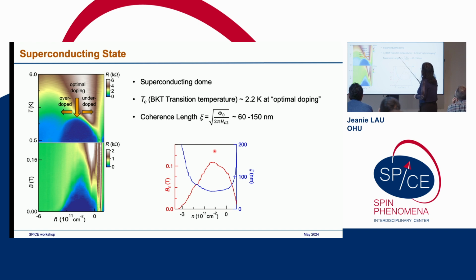The TC we define as 20% of the normal state resistance, and that's 2.2 Kelvin at the highest doping. But the practice these days is to take 50% of normal state resistance, and in that case it will be about 3.1 Kelvin. And that will be the highest superconductivity in twisted bilayer graphene reported.